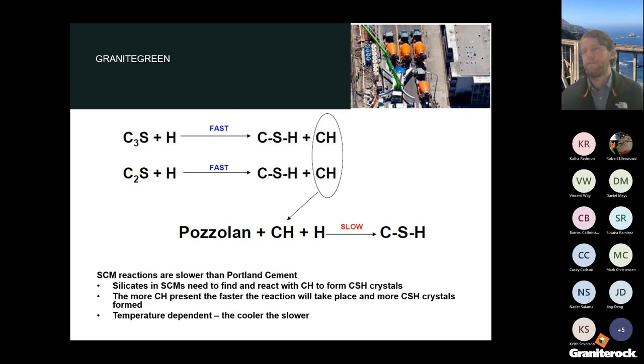Here's a visual of how the chemical reaction of cement and SCMs work together. The hydraulic reaction creates calcium silicate hydrates and free lime. The pozzolan reacts with the free lime to produce more calcium silicate hydrates — the crystals that create strength. When you take out Portland cement you're creating a different product that reacts differently. The reaction is temperature-dependent: when concrete is colder it sets slower, and when it's hotter it sets faster. That's something to think about in low temperatures when using high replacement levels.